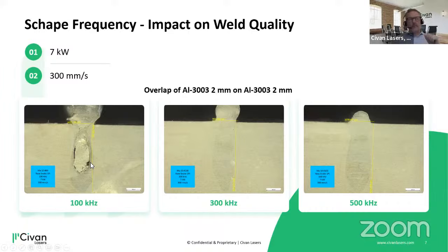You find porosity. You can actually see here this is basically like an eruption of molten material. You go higher in frequency, you already see it stabilizing more. This is still not a wanted topography of the welding surface, but nevertheless the weld inside is already quite nice. But here, in the end, you can achieve something that is acceptable from the top of the weld, and also you have no pores, no cracks. That's basically the goal of any weld seam.